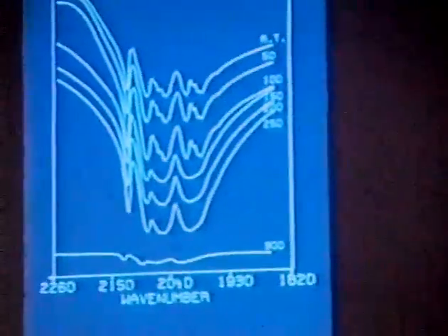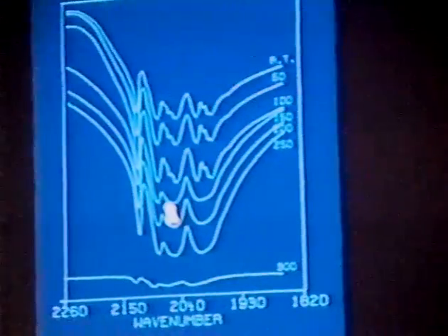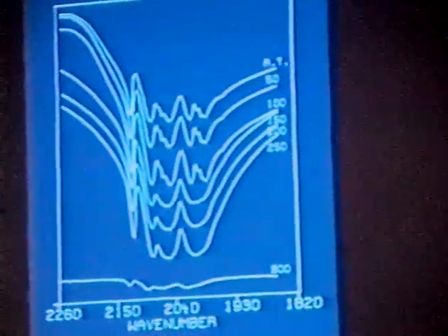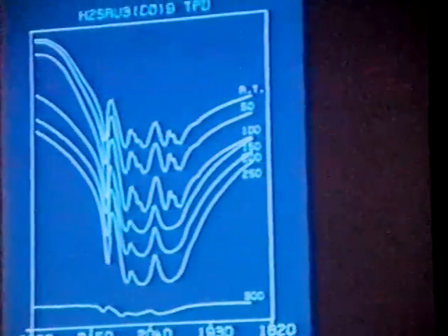During decomposition at elevated temperatures, the spectrum broadens here at 150 degrees. The broadened spectrum is retained to about 250 degrees. At higher temperatures the clusters degrade and transmission falls to very low levels. This is for the ruthenium-only cluster.